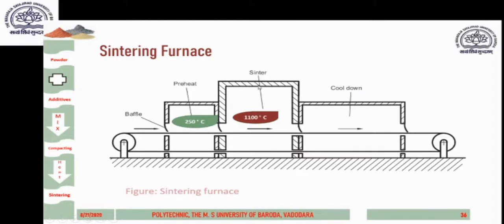Similarly, there is the sintering part of the furnace where the temperature is around 1100 degrees centigrade, and once the part enters this area, it should remain here for around 2 or 3 hours or so, depending upon the bonding strength required and the metal and alloys used for making the powder metallurgy component. This is very important. The belt may be stopped once the part reaches this point, but it is a continuous process, so the belt will keep on moving slowly.